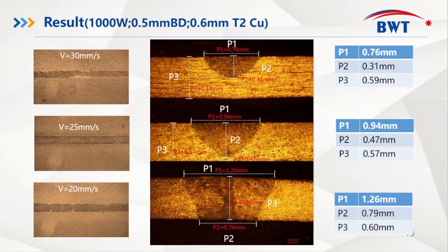The thickness is increased to 0.6 mm and the power is increased to 1 kW at the same time. The speed of 20 mm per second can penetrate. The width of the weld bead on the top surface is 1.26 mm. The bottom width of the weld bead is 0.79 mm.